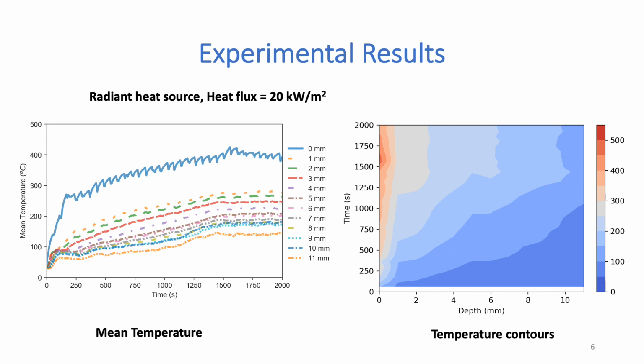We see on the exterior side where it's facing the heat source, we see a spike in temperature as the paper begins to pyrolyze and then later burn on that side. So the combustion of the paper shows a spike, and you'll see this consistently in our work. But then internally, you can see the temperature slowly rise throughout. And this is the 20 kilowatt per meter squared radiant panel test. Another way of showing that is the contours that occur internally, and that's shown on your right here.